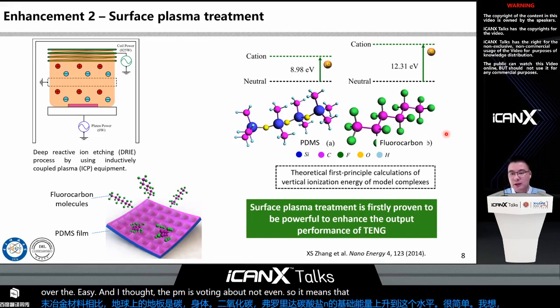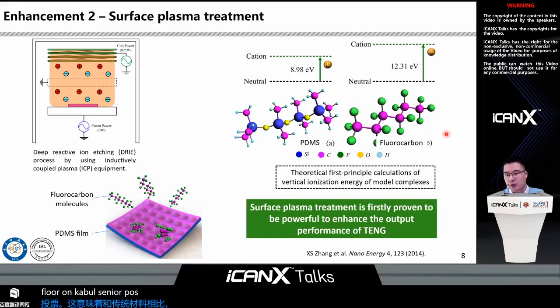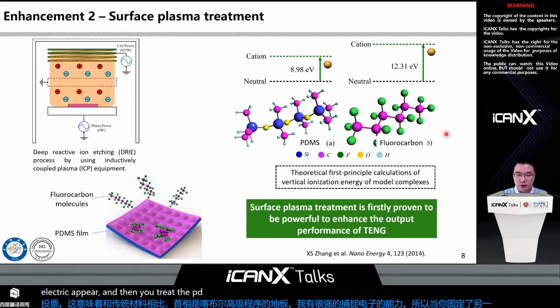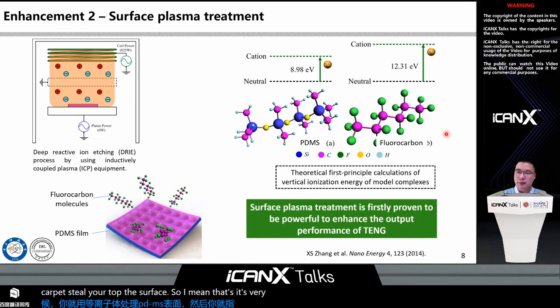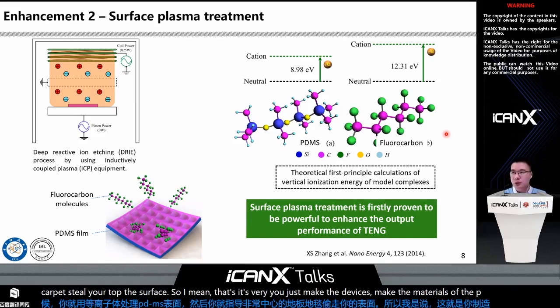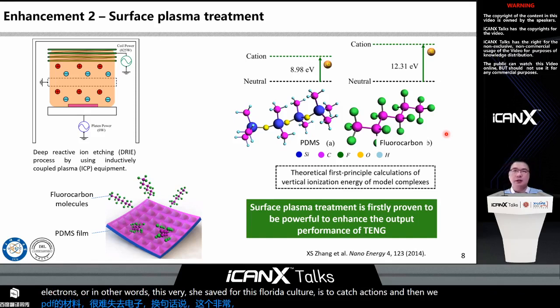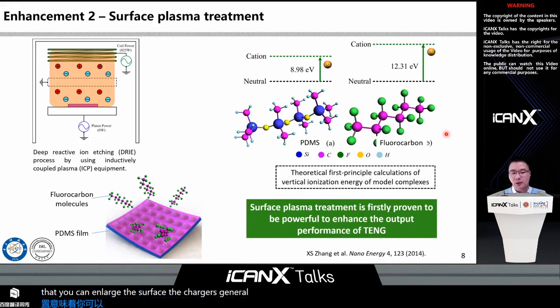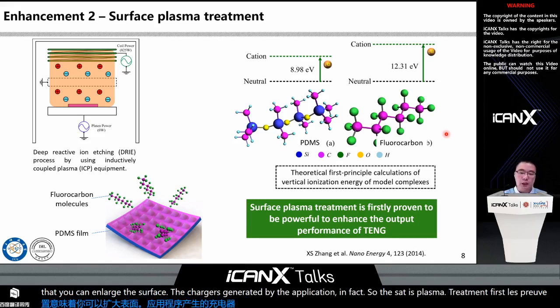So it means that compared with the traditional material, the PDMS, the fluorocarbon thin layer possesses a very strong ability to capture electrons. So when you fix another material serving as the triboelectric pair, and then you treat the PDMS surface by using this plasma treatment and coat the very thin fluorocarbon layer atop the surface, it means that the PDMS is harder to lose electrons, or in other words, it's very easy for this fluorocarbon material to capture electrons, and then we can enhance the output performance of the devices. It means that you can enlarge the charges generated by the triboelectrification effect. So the surface plasma treatment is firstly proven to be powerful to enhance the output performance of the devices. So that is the second enhancement method we developed.